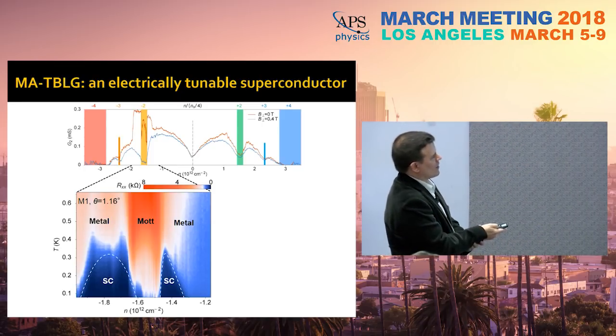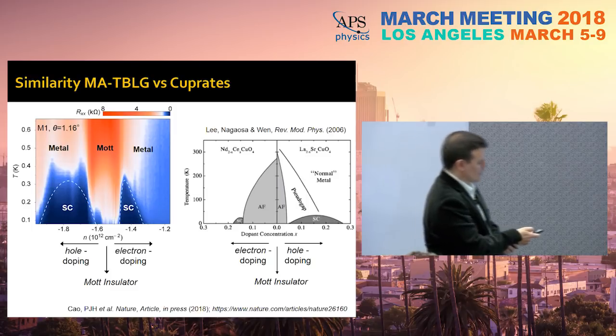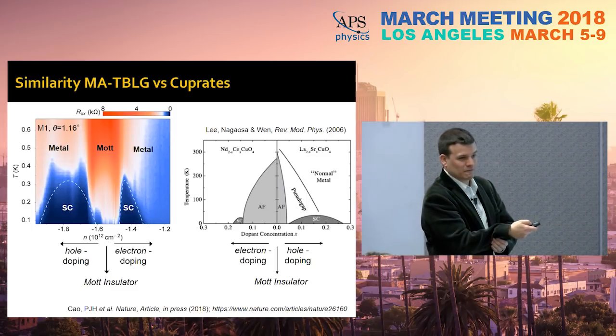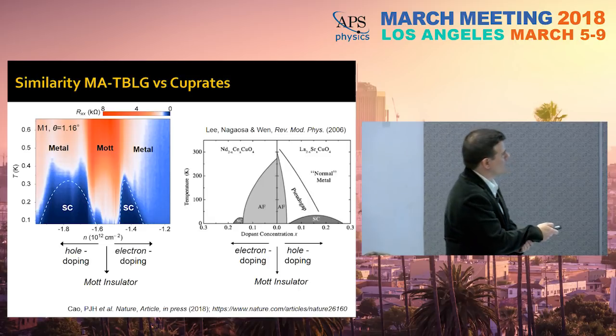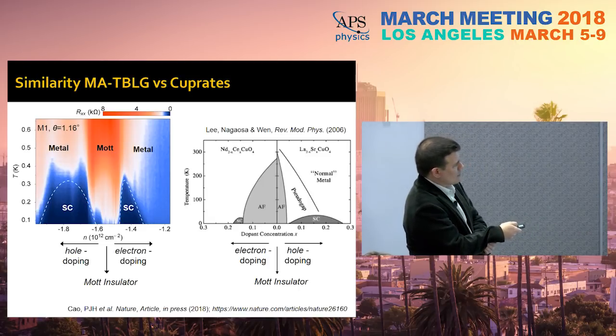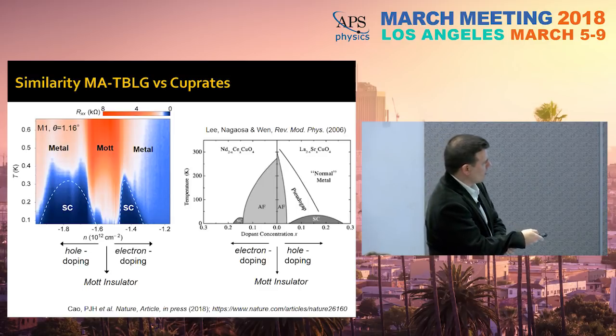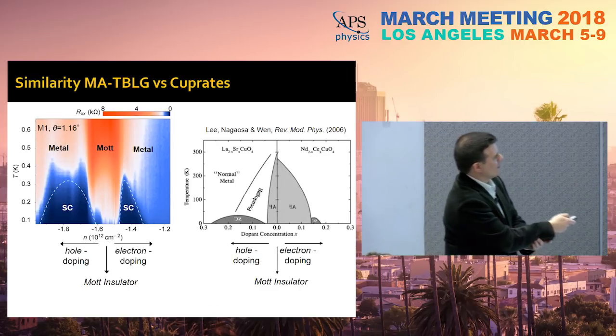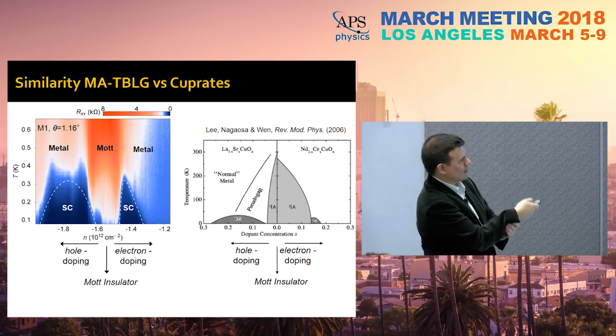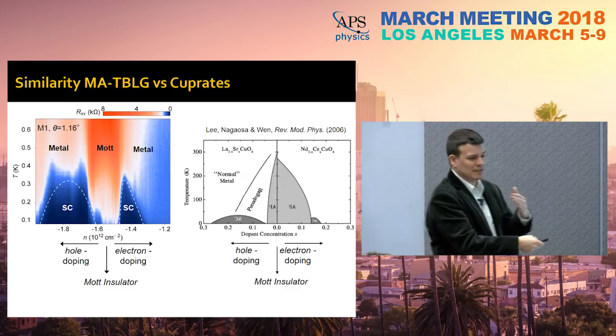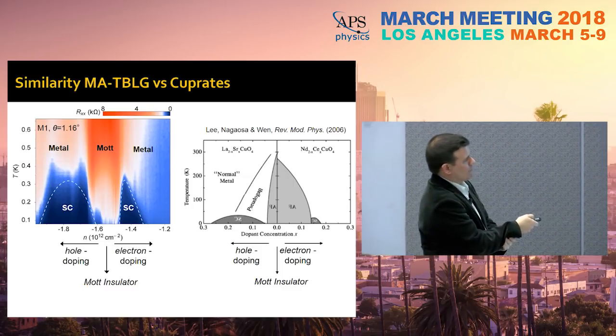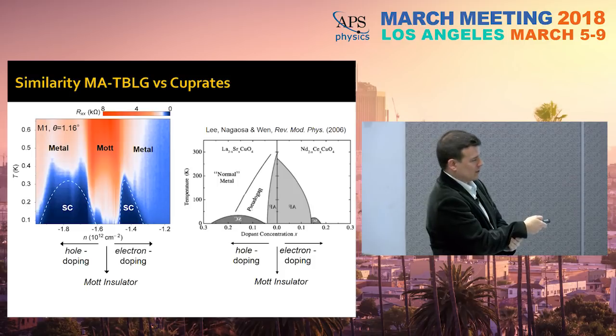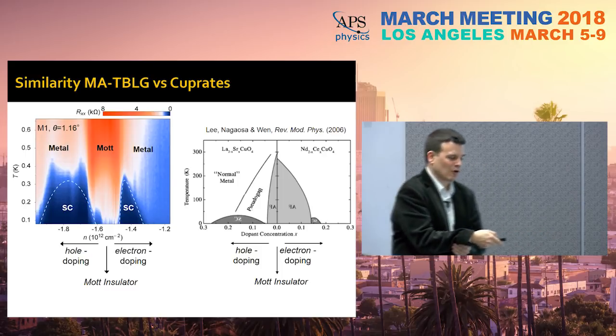When we saw this, we were pretty stunned. It immediately drew our attention to the comparison with the phase diagram of the high-temperature cuprate superconductors. Now, in the cuprates, for some reason, they choose hole doping in this direction, electron doping in this direction. Let me actually flip it for you. So now we have a Mott insulator state at zero doping, which means half filling for the cuprates. If we dope with electrons, we have a smaller superconducting dome. If we dope with holes, a more robust, wider superconducting dome. You can see that we also have a smaller superconducting dome for electrons, a wider one for holes, okay?